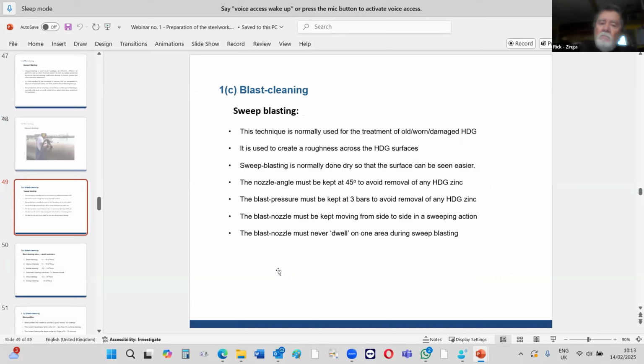Sweep blasting. Again, if you're using Zinga on hot dip galvanizing, we do lots of repairs on galvanizing worldwide. Sweep blasting is a set technique. You hold your nozzle at 45 degrees, not 70 degrees like normal blasting. It's 45 degrees, and instead of blasting at 6 bars, you blast at 3 bars at that shallow angle.